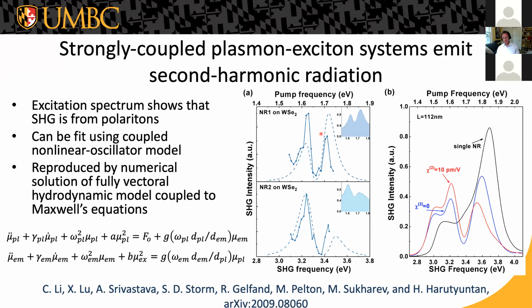In these systems, presumably you have many excitons. This is in the collective strong coupling regime, right? Because your nanoparticle is big, and then there are several excitonic transitions that you're coupling to. Am I correct? Yes, it's hard to count how many excitons are involved in the TMDs. The excitons are delocalized throughout the TMD, right? So it is a collective coupling of excitons in the tungsten diselenide to the plasmon.